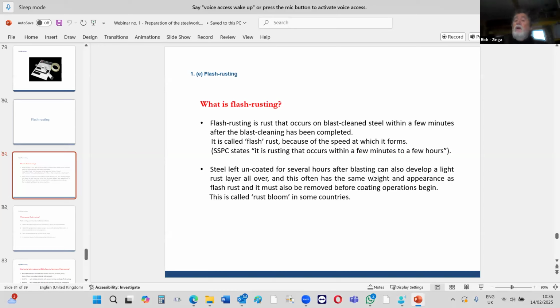And they said, we were told that rusting is bad. I said, no, light flash rust, okay? Flash rusting happens on the peaks. So you have your valleys, but you have your peaks. They are the highest part of the metal exposed to the atmosphere. So the peaks have flash rust on each peak. When you stand back a few meters, it looks like all the metal is orange. But if you go up close with a torch and put it on the surface and angle the torch towards you slightly, you'll see a metallic sheen coming off. So the valleys are not rusted, only the peaks.